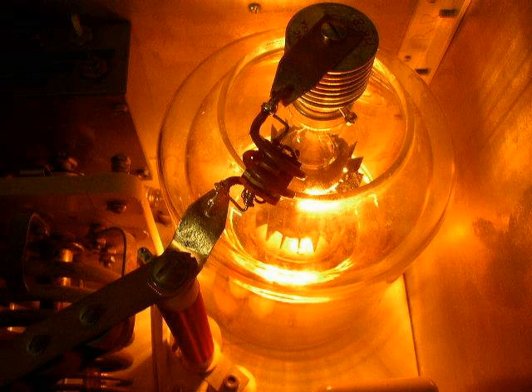Coated cathode: in these the cathode is covered with a coating of alkali metal oxides, often barium and strontium oxide. These are used in low power tubes. Thoriated tungsten: in high power tubes, ion bombardment can destroy the coating on a coated cathode. In these tubes, a directly heated cathode consisting of a filament made of tungsten incorporating a small amount of thorium is used. The layer of thorium on the surface, which reduces the work function of the cathode, is continually replenished as it is lost by diffusion of thorium from the interior of the metal.